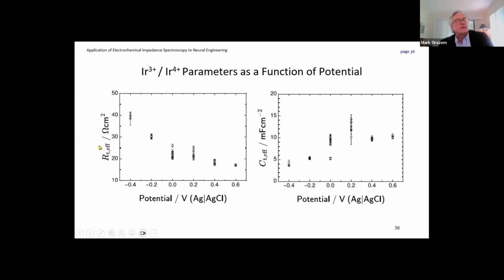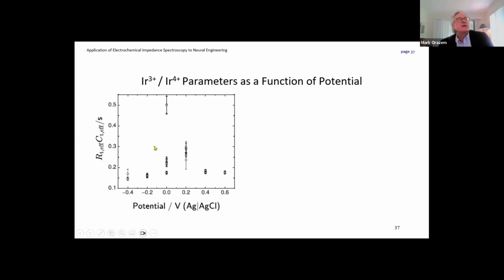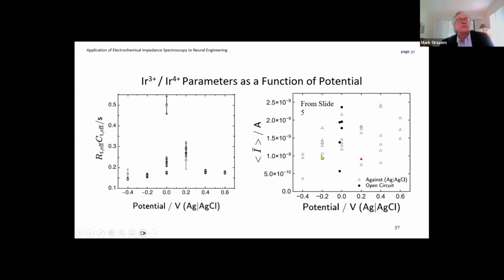If we look at the values for the charge transfer resistance for the iridium, we see that it's a function of potential. Capacitance also is a function of potential. And if we look at the RC time constant for the iridium oxidation and reduction, we see that time constant is somewhere on the order of, let's say, between 0.15 seconds to maybe 0.5 seconds. So that's consistent with our observation that when we waited 15 seconds between measurements, we had waited long enough for this reaction to have stabilized.